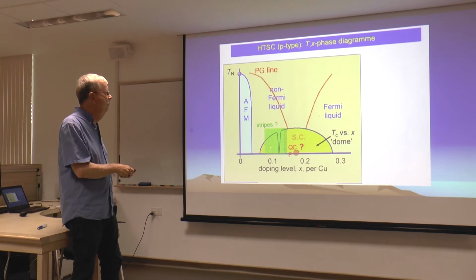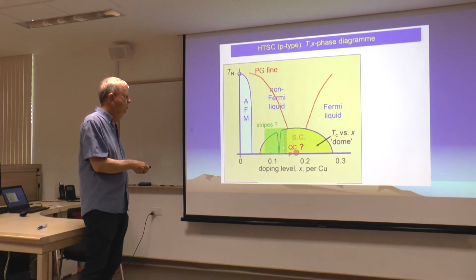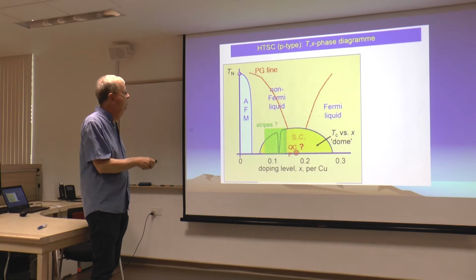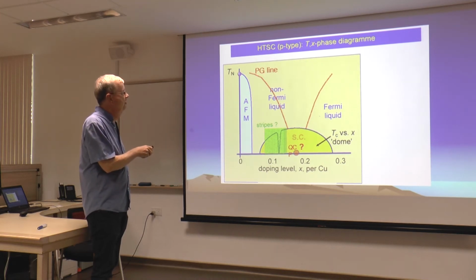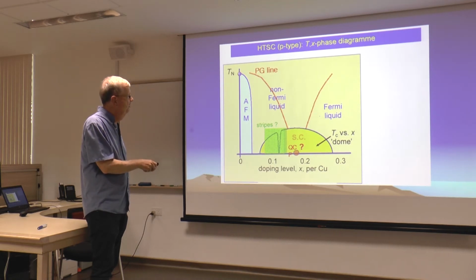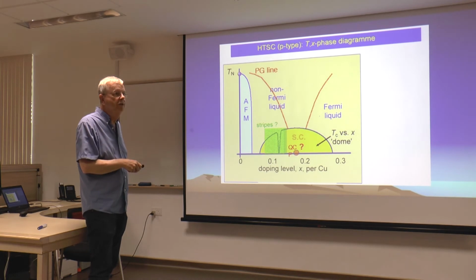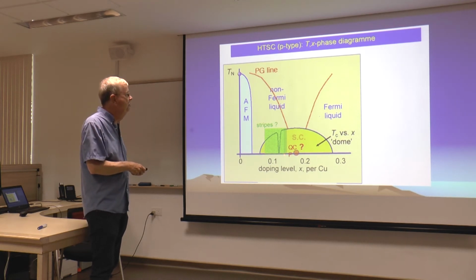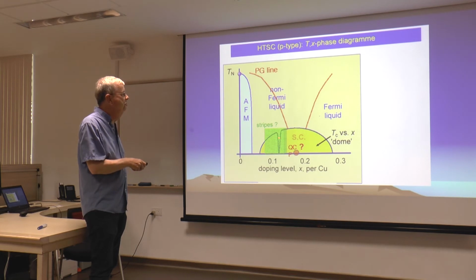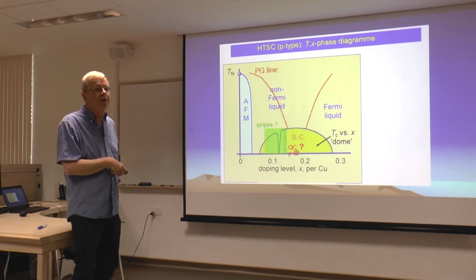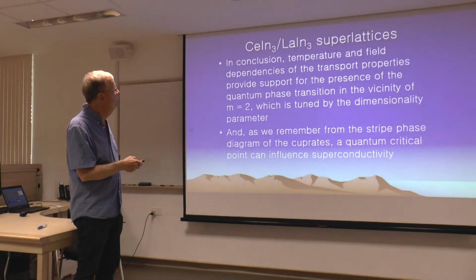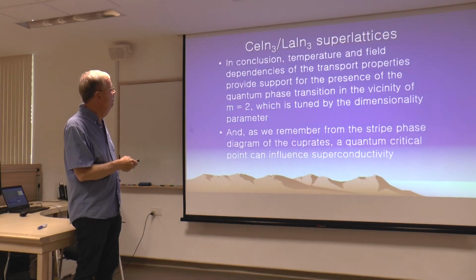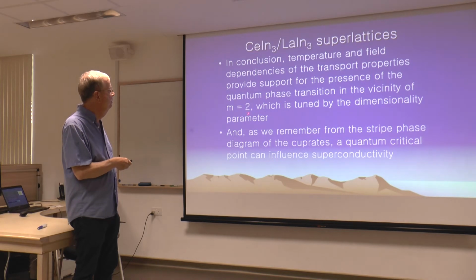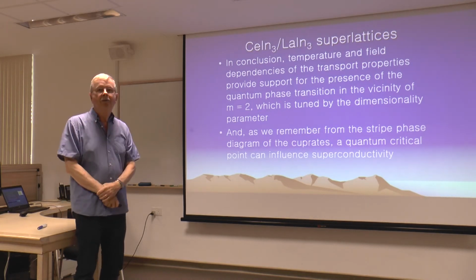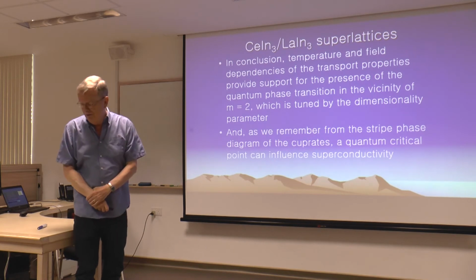So it's very often the case, also in the iron-based superconductors, that when you have your superconducting dome, you have some second order phase transition like anti-ferromagnetism in the iron base that's being suppressed, and the anti-ferromagnetic transition runs into the peak of the dome. Okay? So if you can tune your quantum critical point, you can also tune across your superconducting dome. So the point of the story is you learn something about quantum critical behavior. You've learned something about tuning with dimensionality, and I'm going to let you go early. Thank you very much.